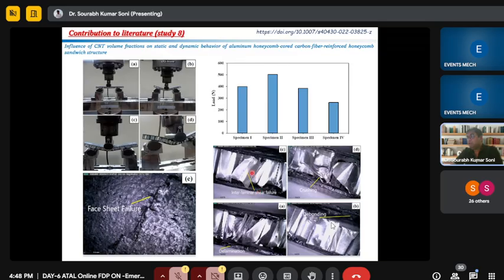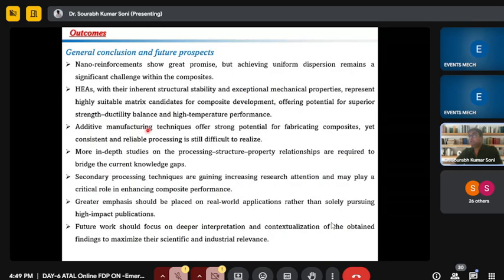This is a failure of the honeycomb structure. Different specimens show different failure mechanisms, so we can analyze that also. I have performed diverse investigations, so I cannot conclude all the studies in a single PPT, but every study has a different conclusion, which you can find in my publication. But as a general conclusion I can say that nano reinforcements are most promising, but we have to uniformly disperse the nanoparticles within the composite specimen. That is a major challenge we need to overcome.